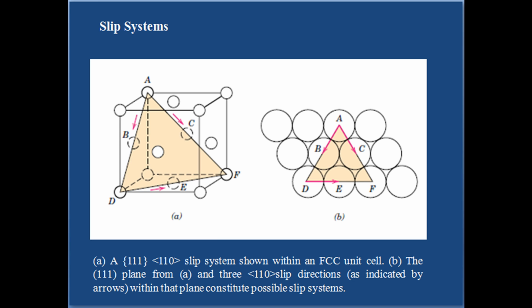For each of these structures, slip is possible on more than one family of planes, for example, {110}, {211} and {321} for BCC. For metals having these two crystal structures, some slip systems are often operable only at elevated temperatures. Metals with FCC or BCC crystal structures have a relatively large number of slip systems, at least 12. These metals are quite ductile because extensive plastic deformation is normally possible along the various systems. Conversely, HCP metals having few active slip systems are normally quite brittle.